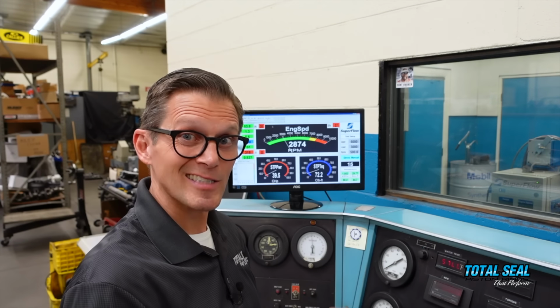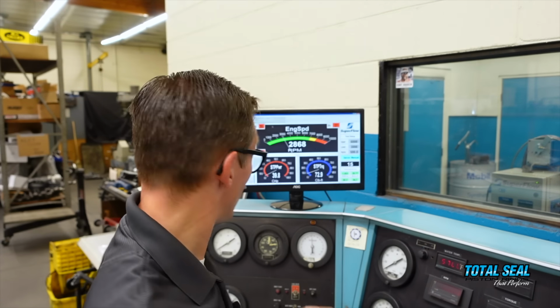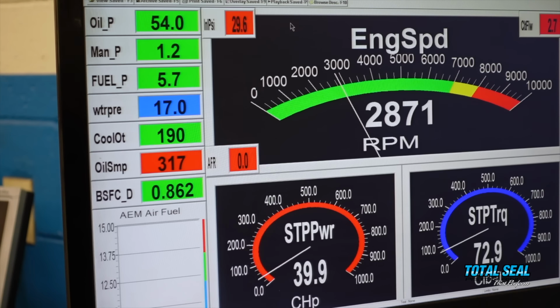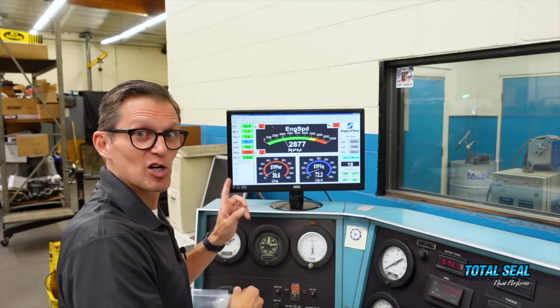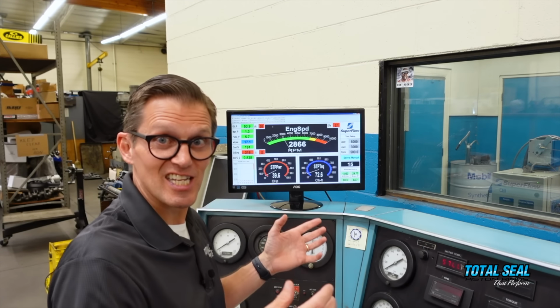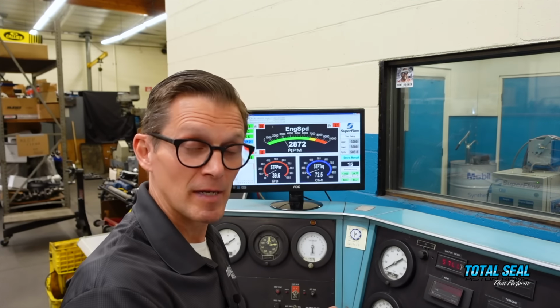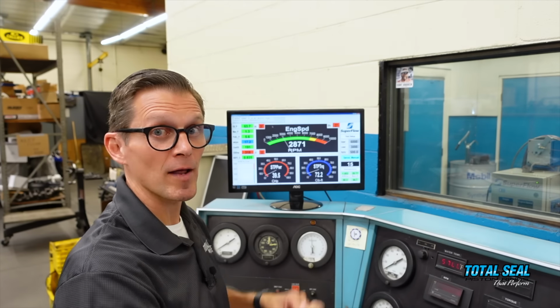Okay, that's 30 minutes. Time to shut it down and let it cool down because, woo, 318 degrees oil temperature. That's the hottest oil temperature I've ever seen during break-in with these 16th, 3/16th rings. So gotta shut it down and let it cool down, and then we'll make the power runs.